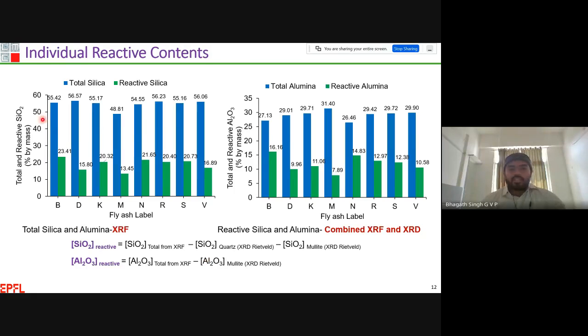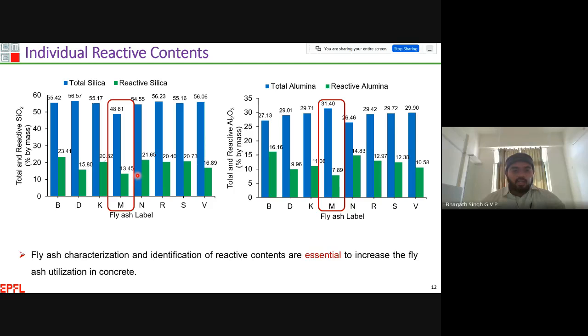As you can see, the total silica as well as total alumina content is more or less the same in all these fly ashes, with very little difference. But the reactive silica as well as reactive alumina content varies significantly from one source to another. Let me focus on one particular fly ash. If you look at fly ash M, out of 48% of total silica, we have about 13% in reactive form, whereas out of 31% of total alumina, we have about 8% in reactive form. The results clearly say that proper characterization should be done before we use fly ash for any type of application. We should not rely on the total silica and total alumina, which misleads our prediction over a period of time.